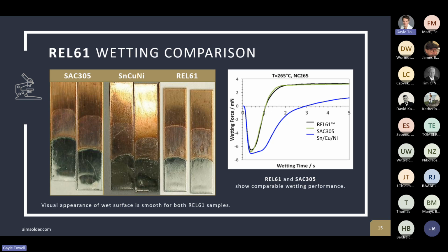This is just another wetting test. So here we can see on the left-hand side just what it looks like visually. We have a nice smooth surface for the REL61 samples. And then on the right-hand side, we have wetting force graphs. And what we see is that REL61 and SAC305 have almost identical wetting force graphs with improved wetting times versus the tin copper nickel alloy.